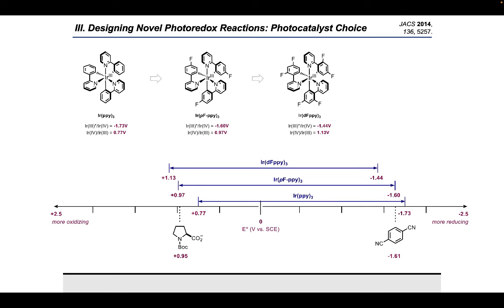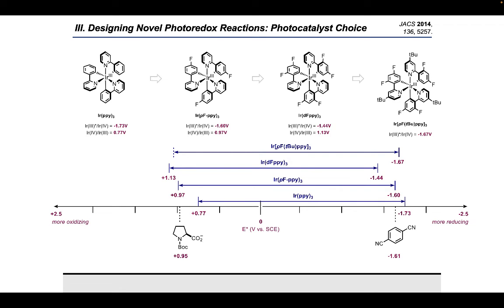With 2 fluorines now, you do get an overpotential for the oxidation event. Compare plus 1.13 volts to the plus 0.95 volts of N-Boc proline. However, on the reduction side, you're now endergonic. So how do they adjust for this scenario? They add electron donating groups to the pyridine moiety to recover some of the reduction power.